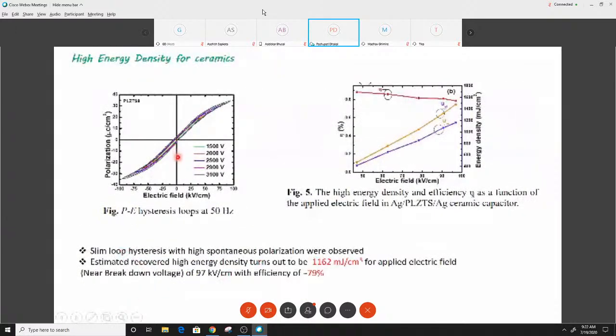This is the P-E hysteresis loop of the ceramic capacitor. We obtain the low remnant polarization and high spontaneous polarization. It gives the high energy density of around 1162 millijoule per centimeter cube with efficiency 79%.